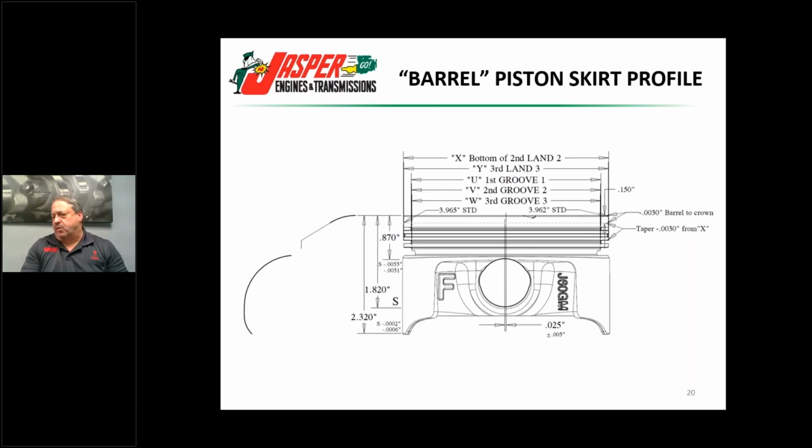If it's a silk screen coating, you'll have an edge to the side that you can measure. So what I would end up doing is find out the difference, the thickness, close to the size point if it's silk screen, and then you can measure that area and then back up. If it's a Mahle D10 or something like that, a spray coating, usually you won't find those over half a thou thick. So what we used to say at Federal-Mogul a lot of times, a skirt coated piston was really a thousandth added on diameter on the average.